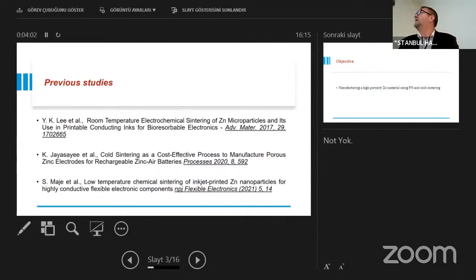There's a second interesting article where they managed to obtain three-dimensional parts, but in order to have good electrodes for zinc-air batteries, you need high porosity. They used a slurry method, mixing the powder with some liquid and sintering them, giving a porosity of about 20%. That's not really a porous material. So except for these groups, I couldn't find anything on the internet about cold sintering and metal, because those old people from NASA say that's impossible - and probably they were almost right.